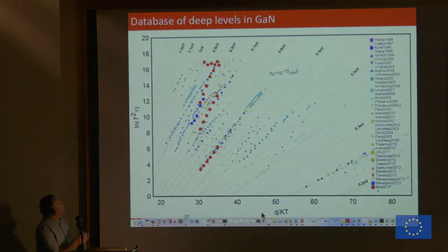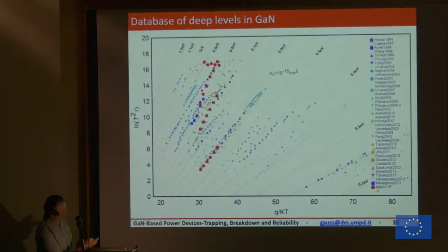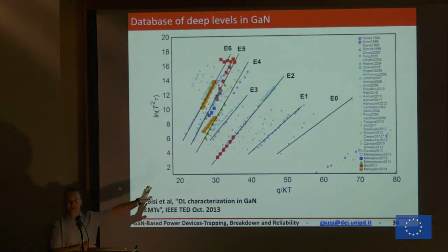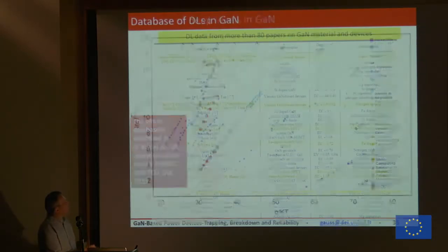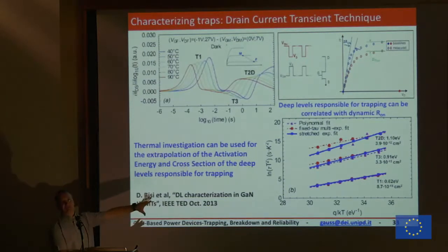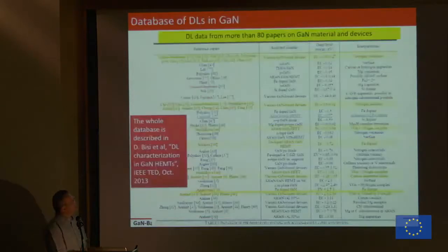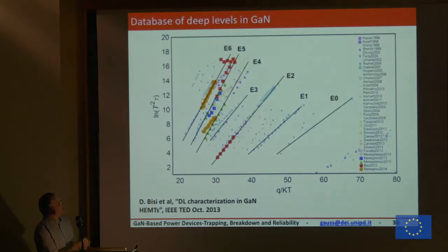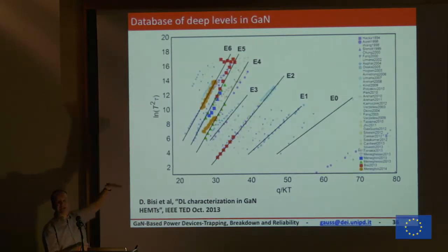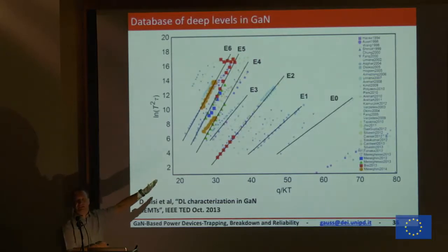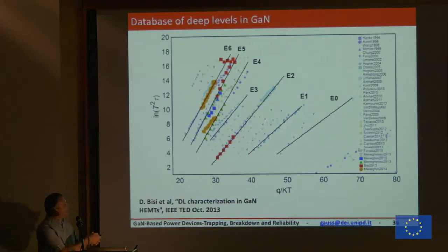As you see, you can see the different activation energies here. What is interesting is that if we take our devices and plot here the traps that we have identified, this one for instance, plus the ones that we found starting from different bias points, we get this result. We found 6 or 7 traps, and you see here our big points, the red, the orange, the green, and so on, within our database. You clearly see that our traps are not just randomly distributed in this plot. We don't see traps with a slope completely unmatched with the ones that are there. Traps are lying exactly in the same direction, and they have some specific activation energy.